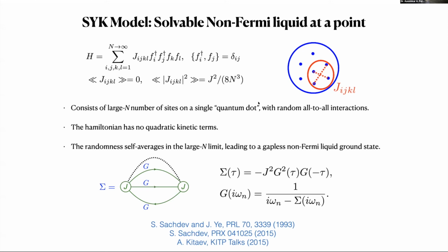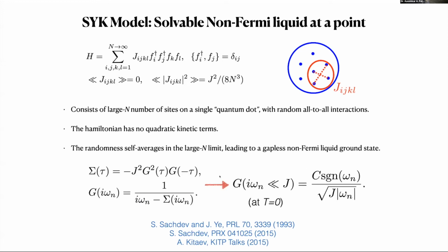Because of the randomness in the interactions, there's an exact relationship which resums to infinite order in J a certain class of diagrams that gives a relationship between the self energy and the Green's function. The solution of those Schwinger-Dyson equations leads to a Green's function that has a power law form at low energies, and it doesn't have a delta function spectral peak that you would expect with quasi-particles.